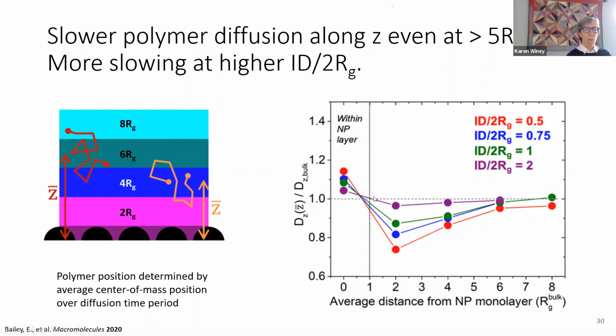We'll talk more about that in a moment. But the big news here is that closer to the nanoparticles, things are slower. Things are slower for higher nanoparticle densities. And then the thing that is surprising, remember the RG, the change in the chain conformation, only lasted about 1 RG. And here the distortion in the diffusion coefficient is out at least 4 or 5 RG.